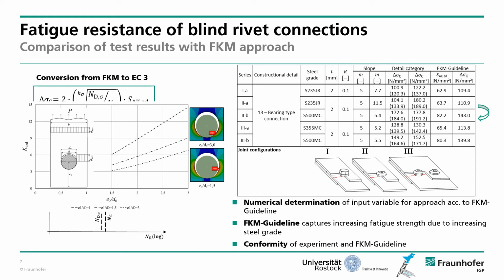And as you can see, the FKM guideline takes into account the increasing fatigue resistance when we use material of a higher strength. And if we now directly compare the detail categories from our test with the detail categories determined by the FKM guideline, we can see there is a really good conformity of experiment and the FKM guideline, and there are not really big deviations between the results, and so we think that this approach or this way to determine the fatigue resistance of such joints is a really good thing.